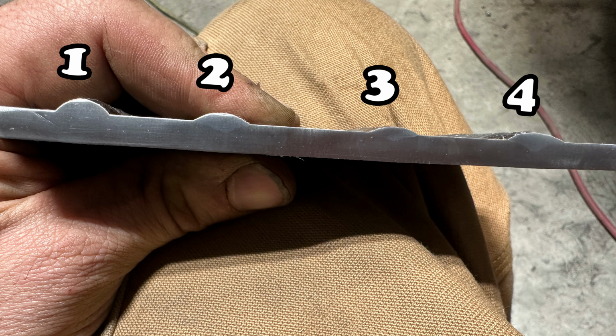So this is Owen's plate, and 1 obviously is the coldest, 4 is the hot plate. When we look at these, and you can't really see 1 very well, but it basically has identical depth of fusion or penetration as number 2. So 1 and 2 are about the same depth. However, much like mine, we can see that as the plate got hotter, the weld flattened out a significant amount.